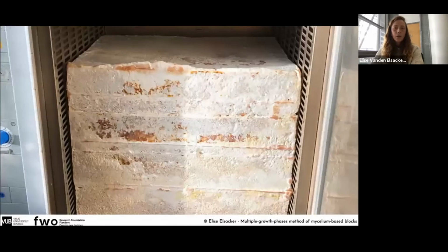And one of the blocks was then dried in a convection oven at 70 degrees during 2 days until the weight had completely stabilized and all the humidity had evaporated. And then the other block was not dried. It was just kept humid. I wrapped it in foil.